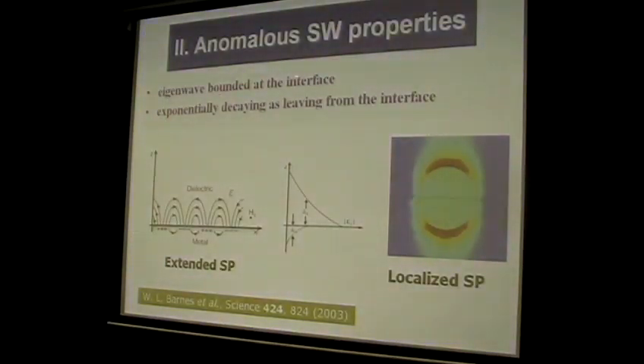So let me go into the second part, the anomalous wave properties of left-handed metamaterials. It possesses very anomalous surface wave properties. So what is a surface wave? The surface wave is actually an eigenwave solution bounded at an interface between air and the metal. This is a very famous picture of the surface plasmon polaritons bounded at the air-metal interface. We can have extended surface plasmons on a flat surface, and also localized surface plasmons on a small particle. Another feature is that the wave will exponentially decay when leaving the interface. This figure is showing the exponential decay.